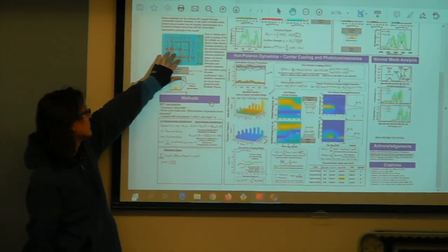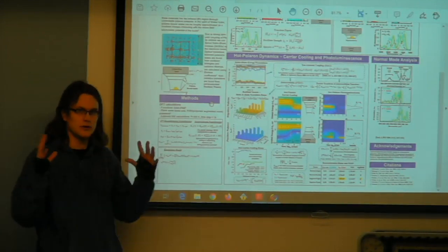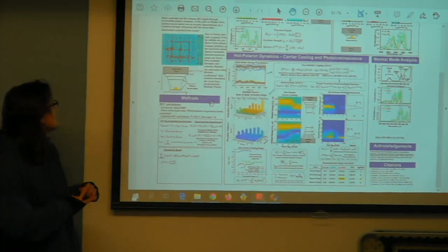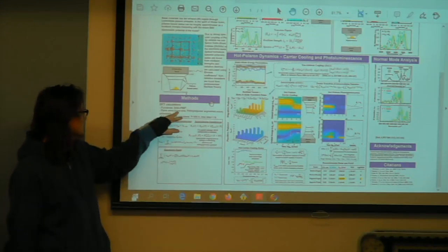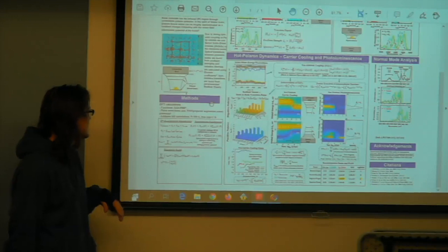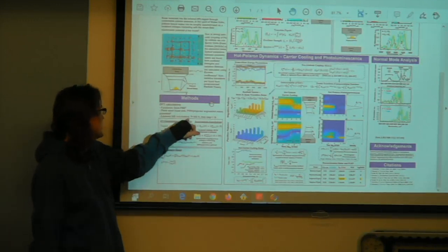So we create a cluster, what we call a nanocrystal, passivate it with ligands, and then model the polaron that forms inside the cluster, so you don't have to worry about charge delocalization in periodic boundary conditions. That's how we set up the model, and the functional that we use is PBE with plane waves. It's all done in VASP, so it's plane wave optimized, and for the dynamics, we implement adiabatic molecular dynamics. We do those at room temperature.